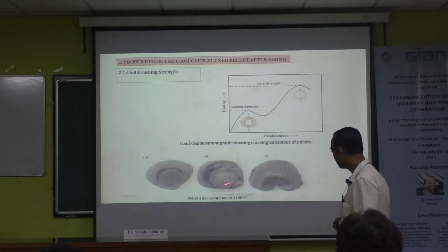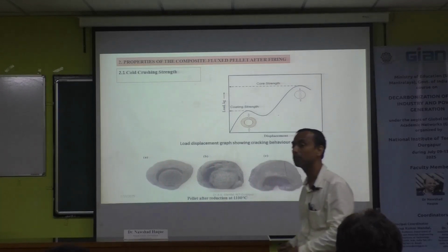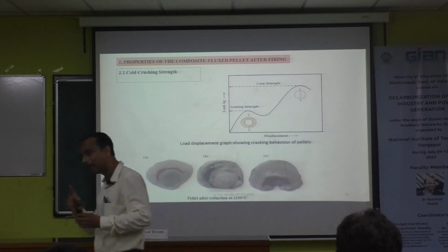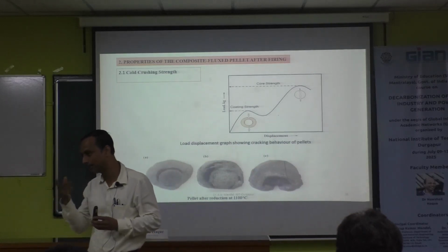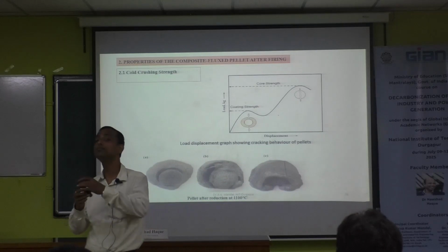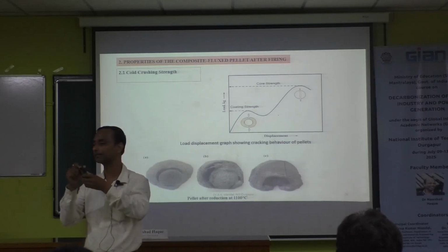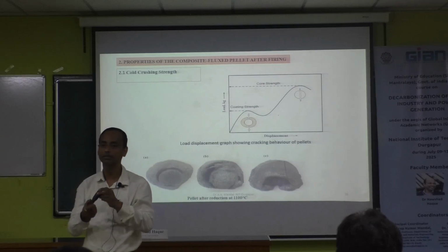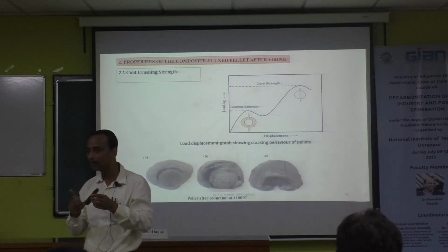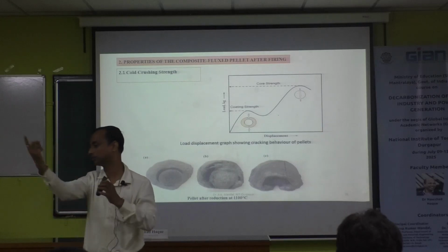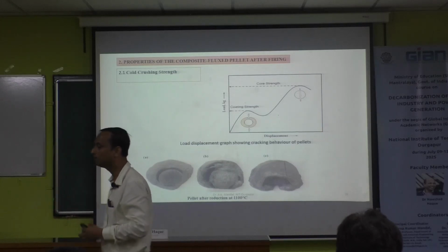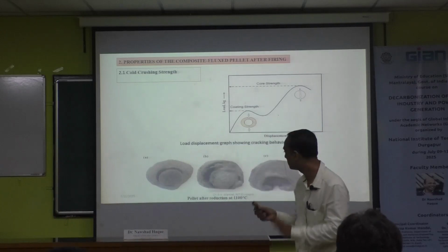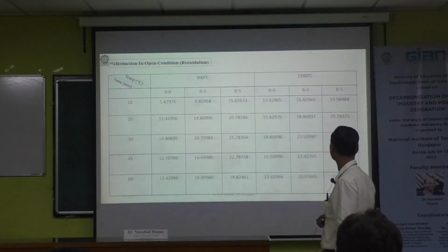You can prepare this one. This was the optimum condition. You can see this one is the lower temperature condition. This is the higher basicity and temperature. Then we propose one mechanism: if the pellet is not stationary during heating, if it is moving, meaning if it rotates, then what will happen? It will not erode. The slag will form a coating throughout the cavity, and it will form the supporting layer which is required, as I proposed here.